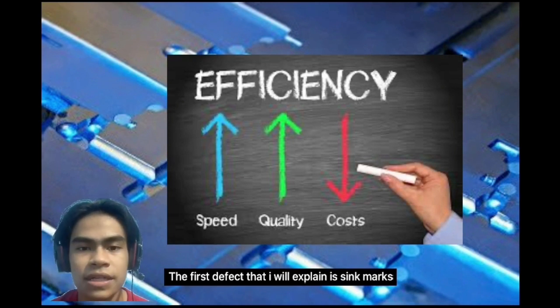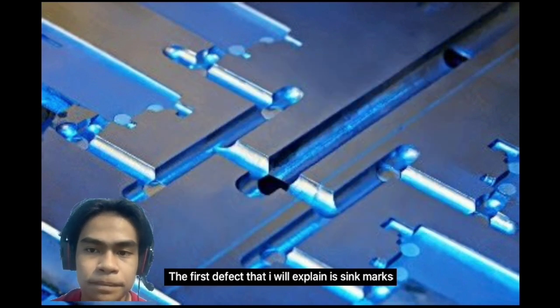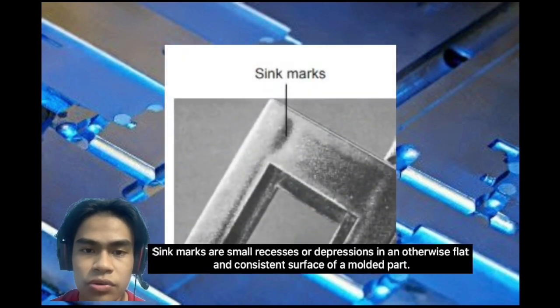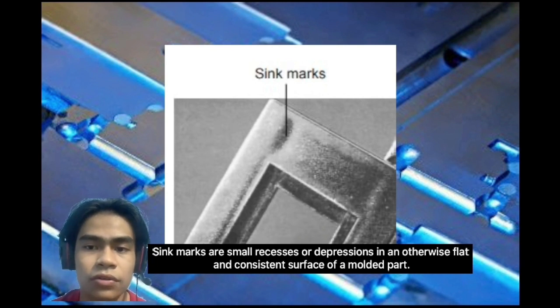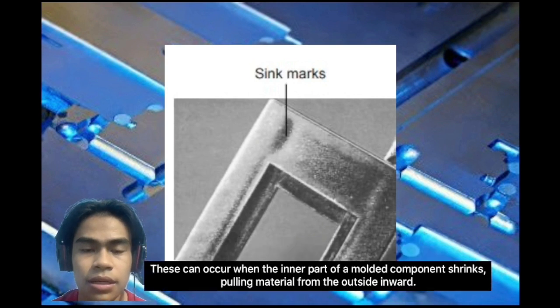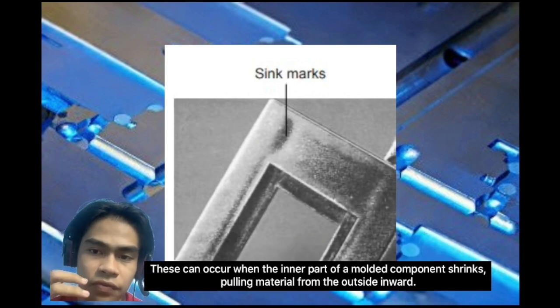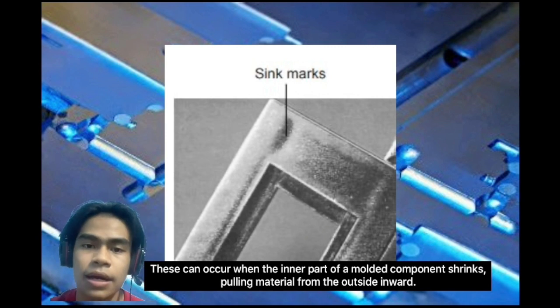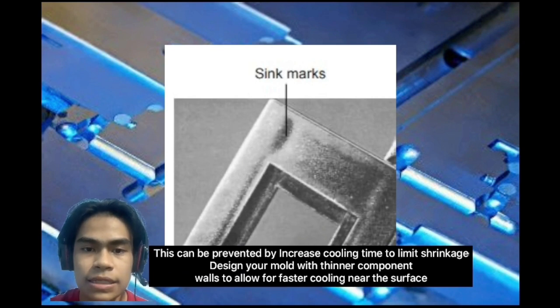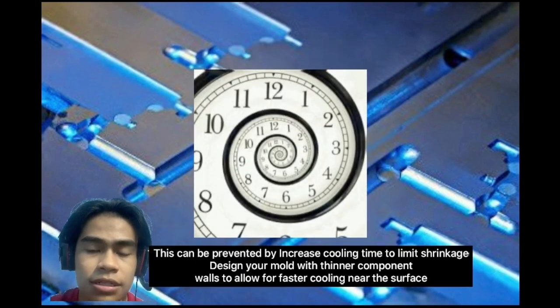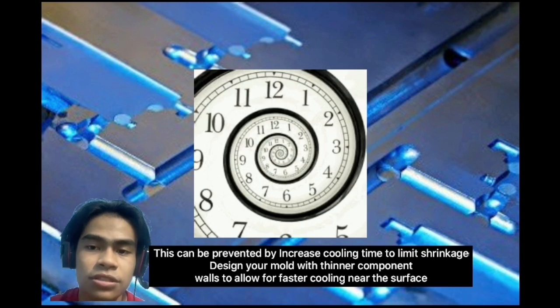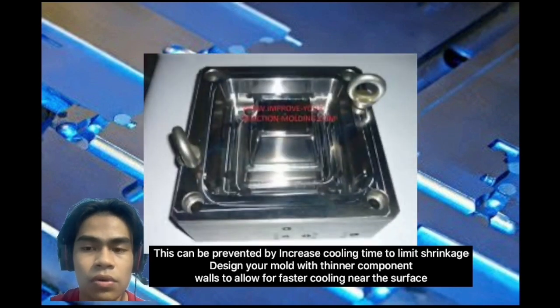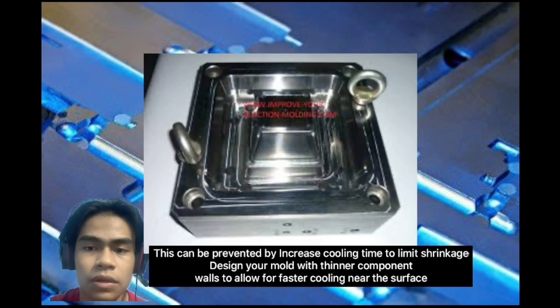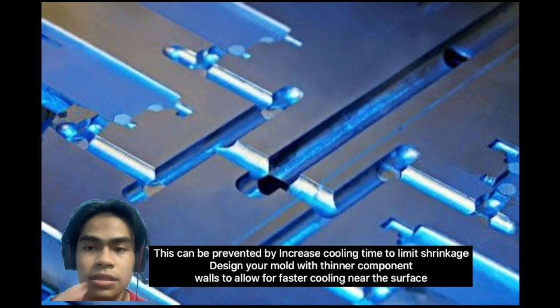The first defect that I will be explaining is sink marks, whereby sink marks are small recesses or depressions in an otherwise flat and consistent surface of a molded part. This can occur when the inner part of a molded component shrinks and pulls the outside of the material inward. This can be prevented by increasing the cooling time to limit the shrinkage, and also designing your mold with thinner component walls to allow for faster cooling near the surface.